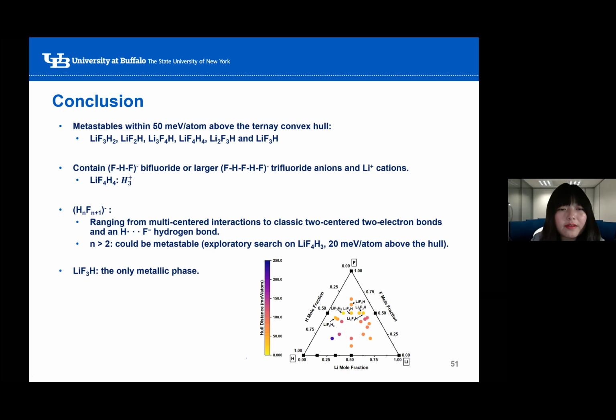And we suspect that when n is greater than 2, there could be more metastable or stable phases. Therefore, we carried out a test search on lithium F4H3 and found a metastable structure with about 20 meV per atom above the hull. And lithium F3H is the only metallic phase.